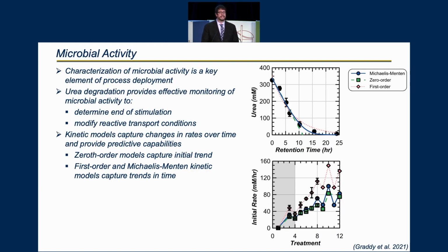Characterization of microbial activity is a key component of this and of any successful process deployment of MICP. Specifically, one of the aspects that can be monitored is urea degradation, an effective means by which activity of the microbes can be determined in order to determine when stimulation can end, when cementation can commence, and how reactive transport conditions can be modified to alter the spatial distribution of the cementation once precipitated in the subsurface. This, of course, can be captured using a variety of different kinetic models over time, and ultimately can be used to provide predictive capabilities when incorporated into reactive transport models.